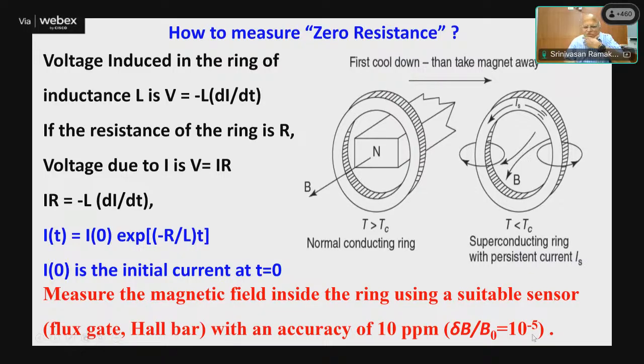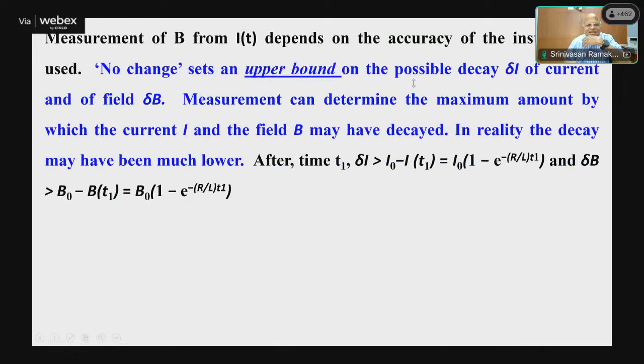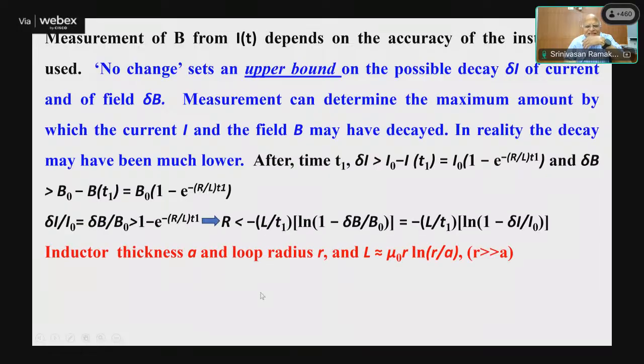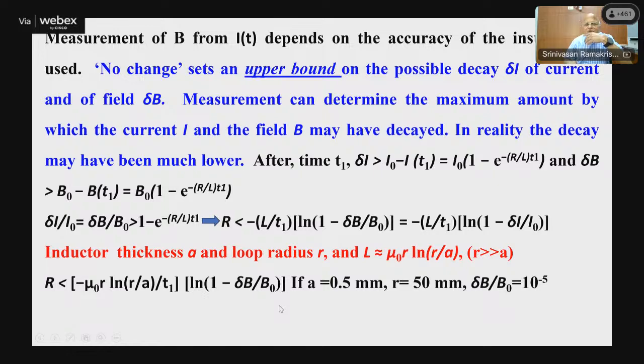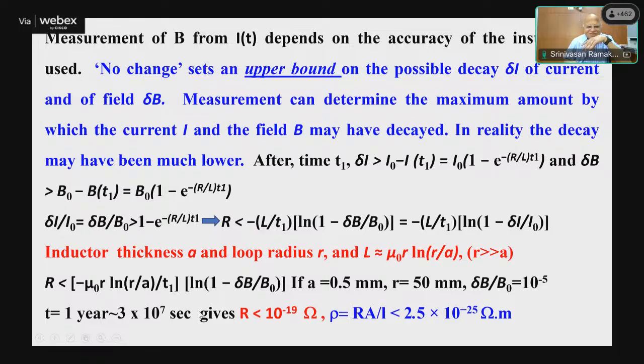The field can be measured to an accuracy of 10 ppm in a standard way, and you can get an upper bound on the resistivity. So for the upper bound of a possible decay, you can find the maximum the current can decay and the field can decay in the ring. I'm not going to go through this math. It's simple math. If you do this, you will see that the resistivity should be less than 10 to the power of minus 25 ohm meter.